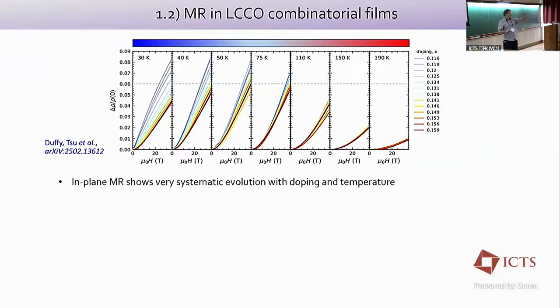And so if you recall that the resistivity is always going to be linear, or still going to be metallic, then actually the change in the magnetoresistance is even more dramatic. And this is unusual because we normally expect for a metal that the magnetoresistance will just follow omega c tau, and so as tau gets longer as you cool down, then the magnetoresistance will get larger. This is what we call so-called Kohler scaling in metals.